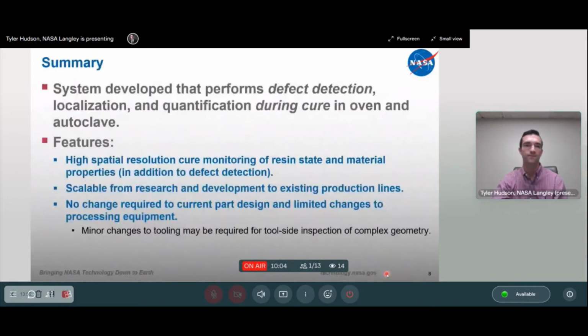processing techniques. So in summary, we developed a system that can perform defect detection, localization, and quantification during the cure cycle. And that's really the emphasis here. There are existing commercial systems that can do it after cure, but this really moves that inspection from the end of the cycle, when there's nothing you can do about it, back into during the cure.